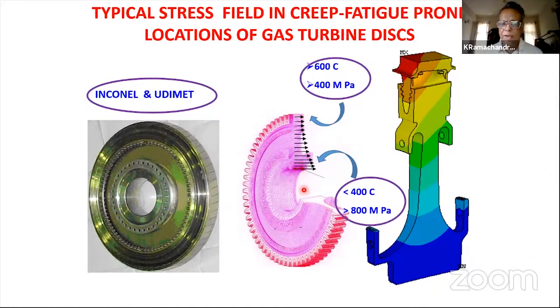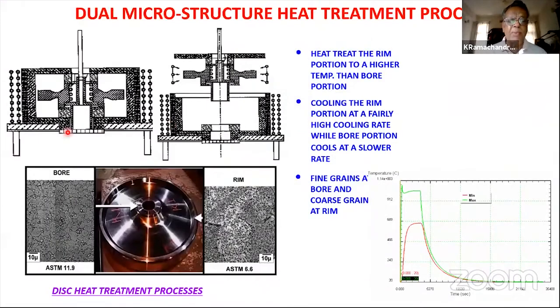So you have a disk which is fatigue critical at the bore and creep critical at the rim. And therefore, whichever is weaker at the end of that period of time, we throw the disk out. And therefore we lose a lot of the benefits of the disk much earlier than what we should be doing. And therefore there is a possibility today. So let's take the same disk and put it